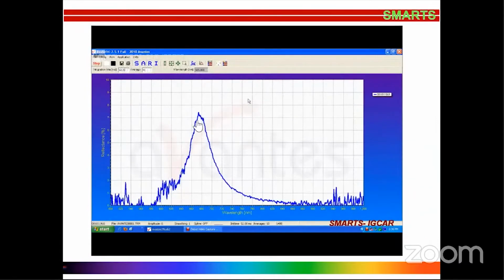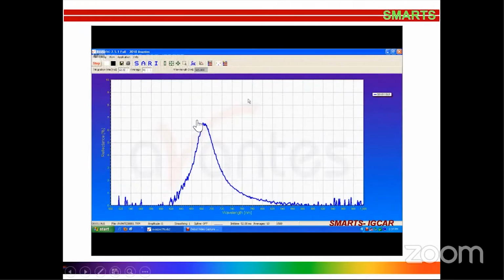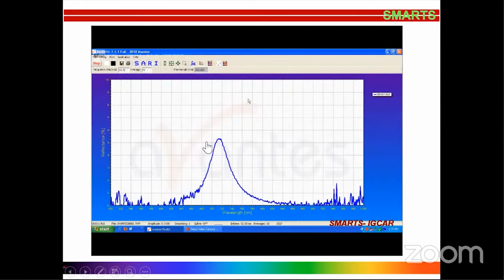And when you decrease the magnetic field, the distance between the particles within the chain is decreasing. That is what you are seeing here in the video. I'm just slowly reducing the magnetic field. You see the Bragg peak is shifting, and this is measured at a constant angle. So you see the interparticle spacing within the chain is decreasing, and at some point the force is not sufficient to keep these particles within the chain, and then it becomes totally disordered. So you don't see any Bragg peak in the system. So you see how you can tune the magnetic interaction and obtain the ordering in the system.